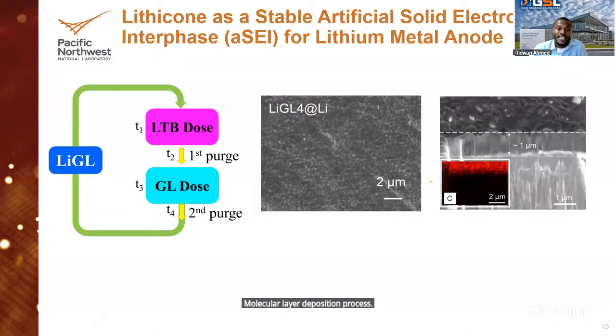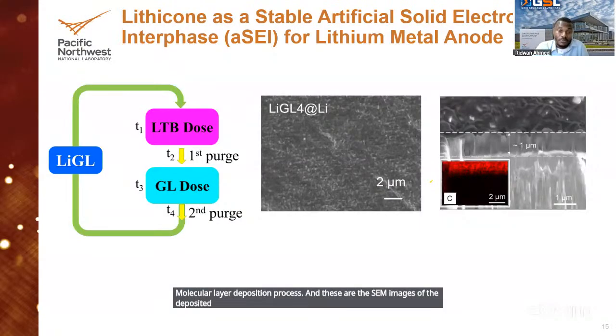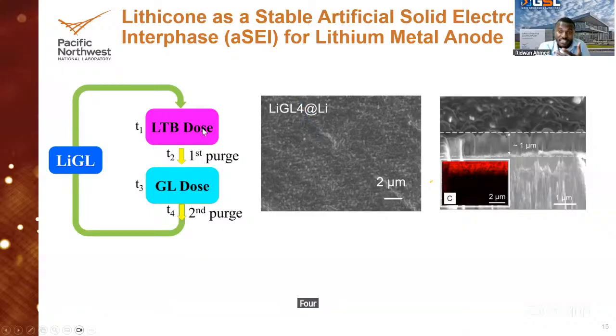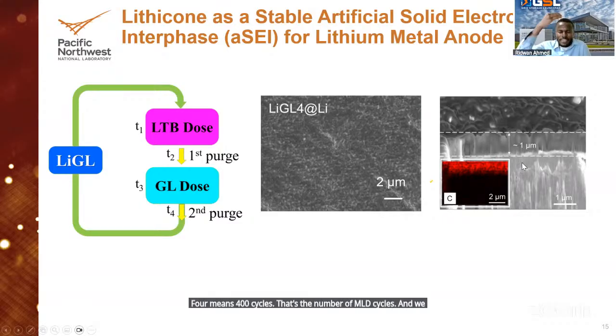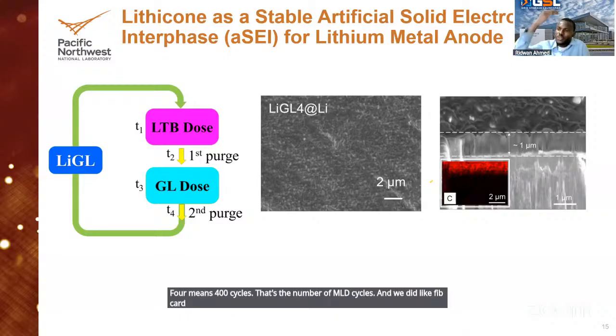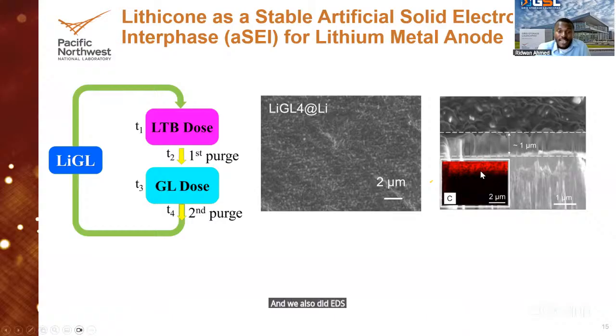And these are the SEM images of the coated lithium. So this is the deposition layer, which is the lithicone. This is the code name, LIGL4. 4 means 400 cycles. That's the number of MLD cycles. And we did FIB to look at the cross section, and then we found out that the coating thickness was actually 1 micron. And we also did EDS just to confirm that this is actually our coating, because carbon is the characteristic element.